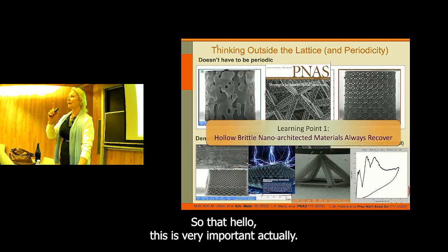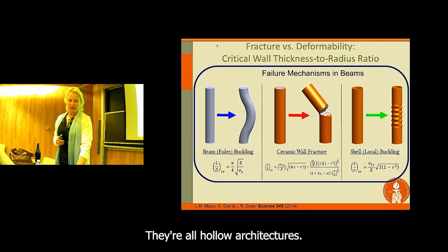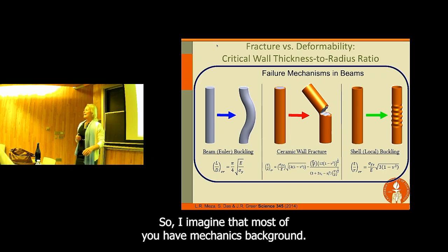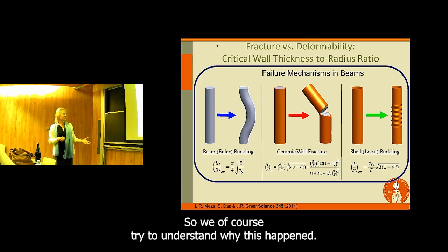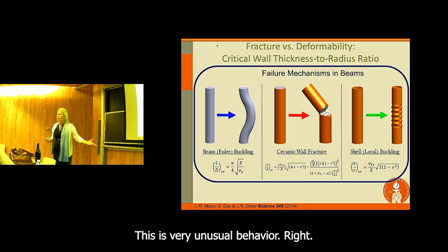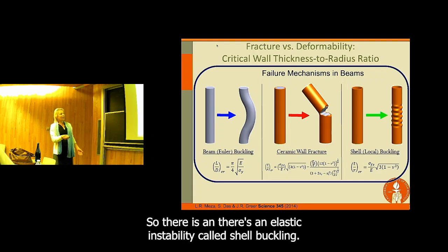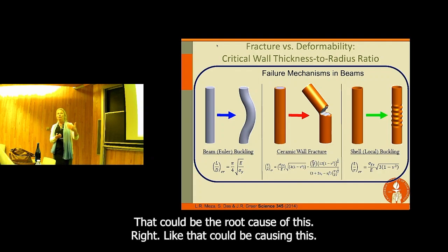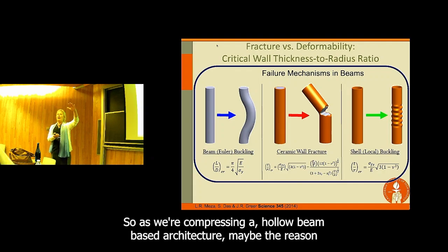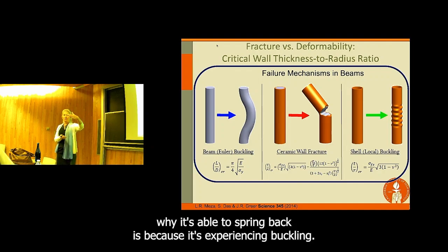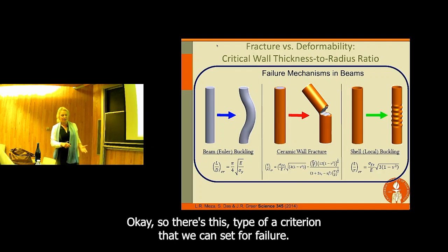Okay, so that hollow, this is very important, actually. They're all hollow architectures. I imagine that most of you have a mechanics background. So we, of course, tried to understand why this happened. This is very unusual behavior, right? So there's an elastic instability called shell buckling that could be the root cause of this. As we're compressing a hollow beam-based architecture, maybe the reason why it's able to spring back is because it's experiencing buckling. Okay, so there's this type of criterion that we can set for failure.